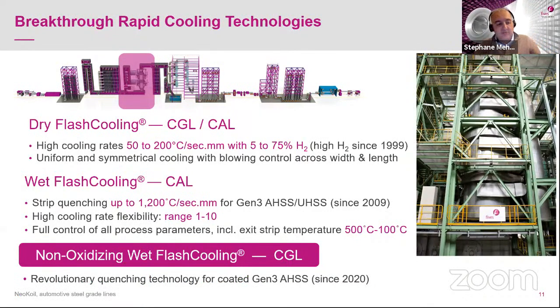And the latest technology that we have developed is really a revolutionary quenching technology, which is based on the same wet flash cooling technology that I explained before, but using water with some additives, which avoid the strip being oxidized. So by developing this technology, we have been able to bring strip quenching up to 1,200 degrees per second into CGL, hot dip galvanizing lines, without inline pickling necessary to be installed. So this technology has been installed recently, and is operating since last year in a new CGL in the US, which is dedicated to Gen 3 advanced high strength steel.